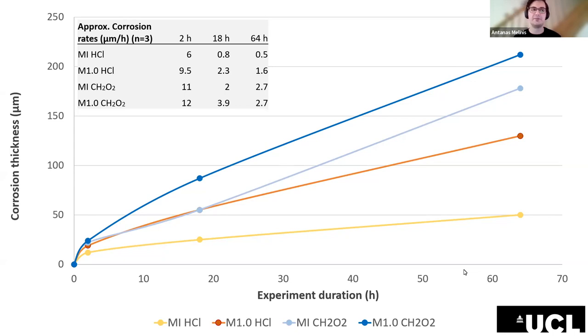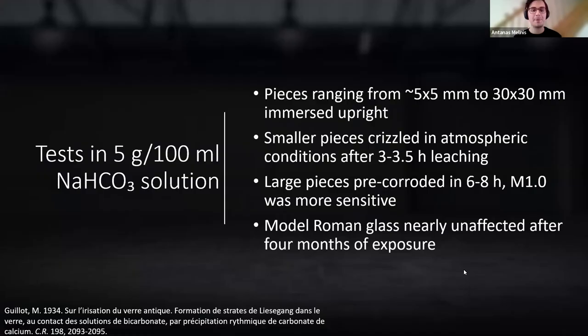Additional tests with formic acid were done on Roman glass, but even after 1 year at room temperature, they've had very little effect, which is very surprising. Surprisingly resilient they've made them. A more reliable acceleration method had to be found that would produce the results within a short time frame.